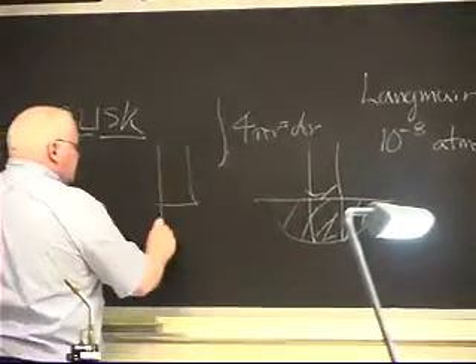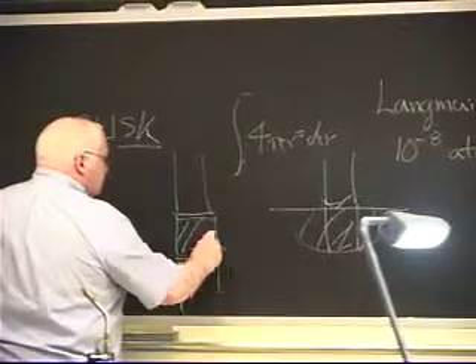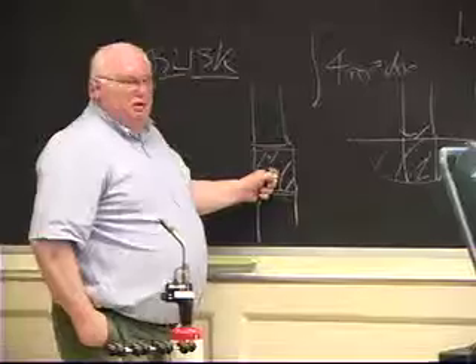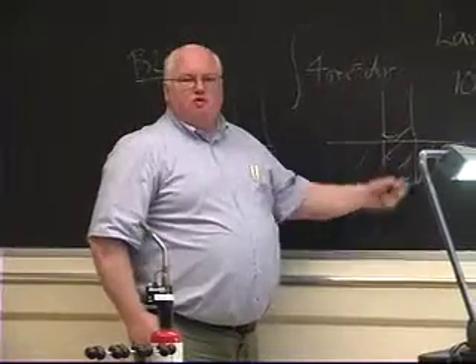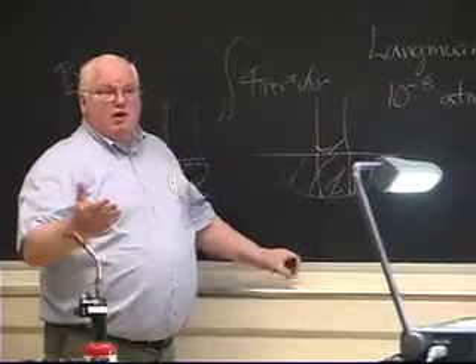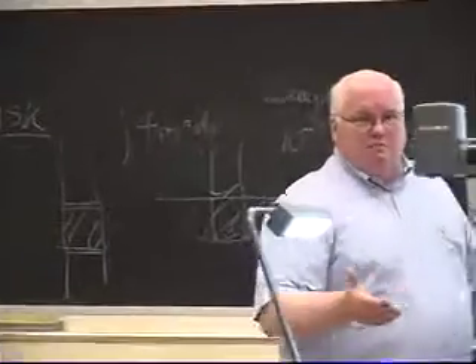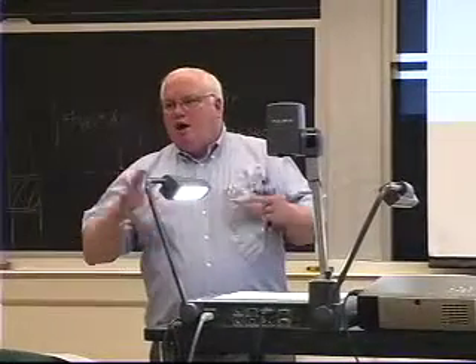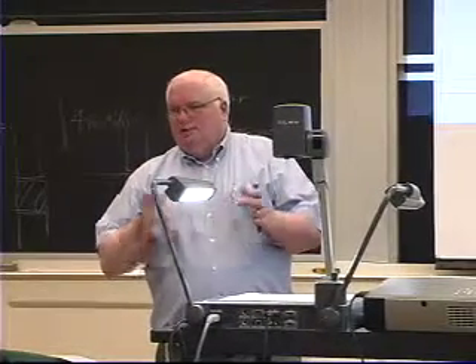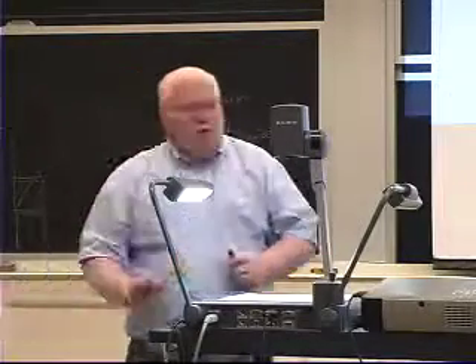If I was squeezing a sample of material between 2 punches like this, that's the volume of material I'd be deforming. But when I'm doing it on an infinite piece of material, I actually am deforming about 3 times as much material. And if you actually look at hardness indentation strengths, they're about 3 times the compressive yield strength of the material. Okay? Just because of the geometry effect. And so you find that when you just squeeze these 2 guys together, you only get about 1/3 contact area. You can squeeze until everything's just starting to flow, but in just straight compressive yielding, you'll still have some voids in there. Okay? So that's a simple-minded way to think about it.